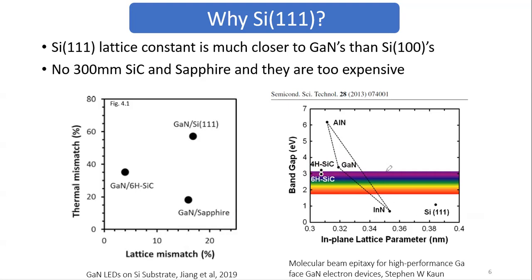And then silicon 111 has a lattice constant of like 3.85 angstrom. That's not too far from gallium nitride. If you compare with silicon 100, well, that's about 5 or more, right? That's close to 6 angstrom. So silicon 111 in comparison to 100 is a better one. Even though you can see that the lattice mismatch is large, the thermal mismatch is large as well.